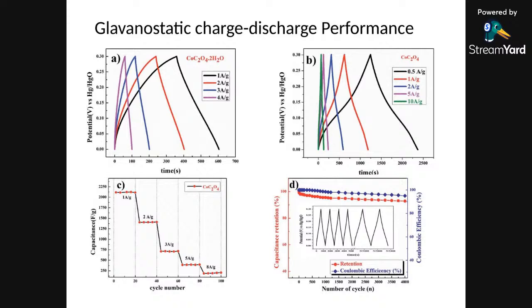So now this capacitor is actually holding the charge for a much longer time, from a few seconds it has gone into a few minutes. So it means we can get battery-type performance in capacitors, releasing much higher energy density. Even at 1 ampere current density, we can hold the charge up to 500 seconds or more, around 8 to 9 minutes. In that case the capacitance is close to 2200 farad. And if you see the energy density at 1 ampere, it will be close to 120 to 130 milliampere hour per gram.